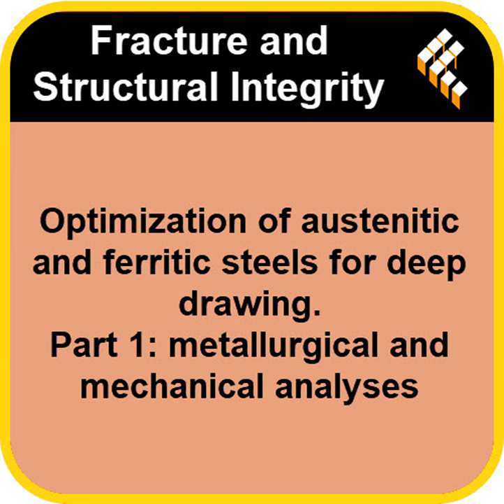Because the metal couldn't slide easily over the punch, the deformation got concentrated. Instead of stretching evenly, the material would thin down drastically in one specific band, usually partway up the side wall of the cup. That's called localized necking. And that's where it fails prematurely. Right. In the very top of the cup, the apex, it barely gets deformed at all because the material flow stalled out.